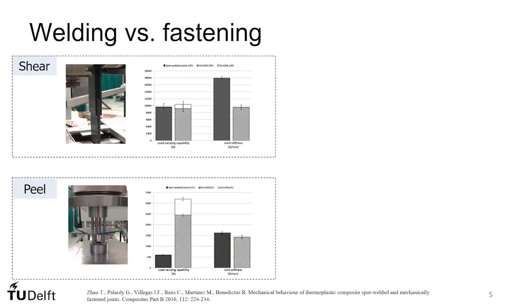First, an ambitious comparison, welded versus mechanically fastened joints. In this study, we followed a stepwise approach in which first we looked separately at the shear and peel behavior of the two types of joints. The welded joint consisting of a 10 mm diameter ultrasonically welded spot and the fastened joint of a single hi-lock fastener. The shear performance of both types of joints was similar.